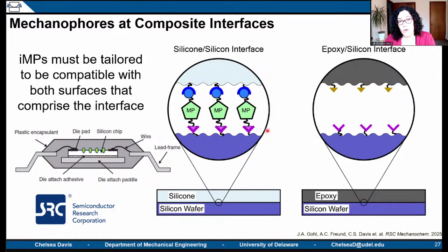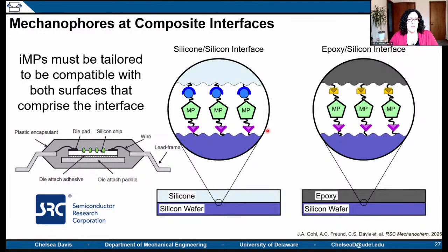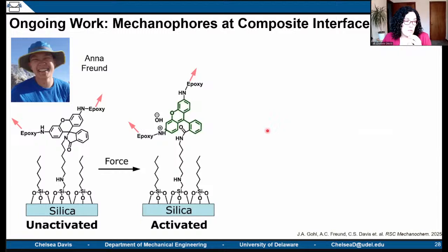So if you're going to have a silicone-silicon interface, that's going to require a different functionality, or a mechanophore with very different functionality than one that you're going to attach between an epoxy-silicon interface. And these are both encapsulating materials that are used in the semiconductor industry. So this is very much ongoing work. All that we've done so far is publish a proof of concept.